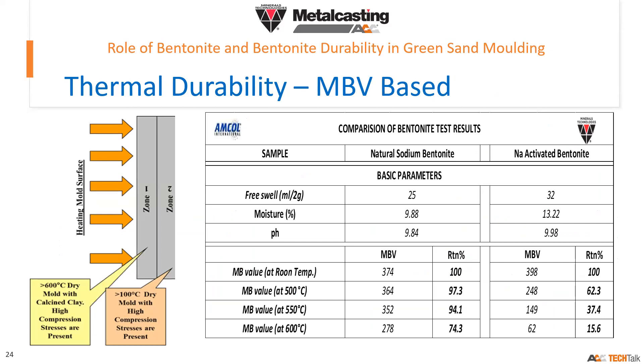As we calcinated or heated the bentonite at 550°C and 600°C, the drop in MBV is substantial. At 600°C, the MBV of natural sodium bentonite is around 278, which is approximately 74% retention. Whereas sodium-activated bentonite dropped from 398 to 62 — only 15% MBV remaining. This drop is quite substantial. However, MBV-based testing alone is not sufficient for qualifying, because we also need to check properties like green strength.